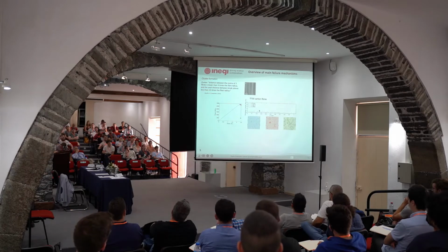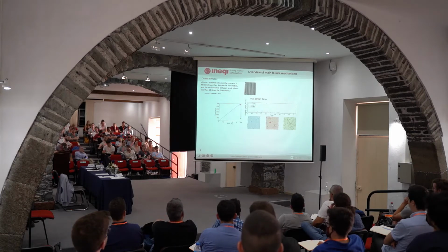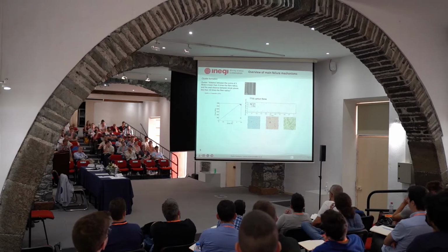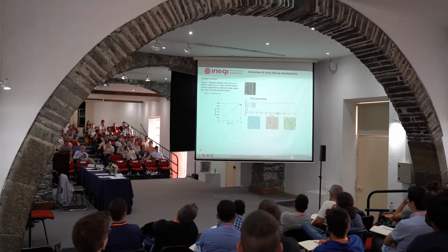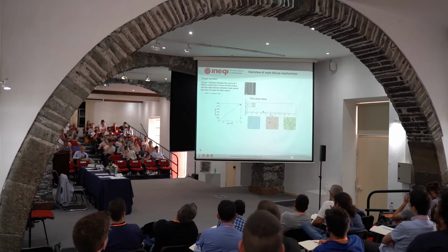And here you can see in a volume, so this is axial position, so it's position along the axis of the fiber, and this is the percentage of broken fibers in one given plane, okay? You have 3 different strain levels, blue, red, and green, okay? So you can see that you are increasing the strain, but in this region, nothing is happening, okay? You don't get more fiber fractures, so all the action is taking place in this region. So you can see that damage is localizing in this region, and you can see exactly that in these pictures here, where these fractures are not all in the same plane, but they are in this volume that you can probably see over there, okay?